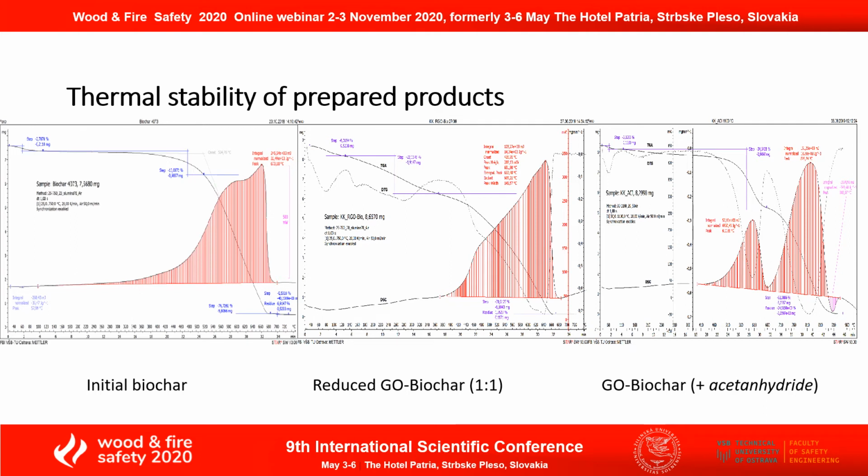In the last chosen spectrum, there was no weight loss up to temperature 400 degrees of Celsius. Reaction was thermally neutral. The thermoanalysis occurred in two stages, in the temperature ranges between 400 to 600 degrees of Celsius and between 660 to 880, with a maximum at 826 degrees of Celsius.